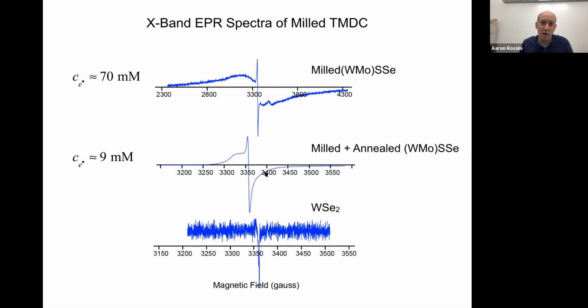We've also done some work on irradiated solids. And we basically see when you get these radicals that have very large g anisotropy, they're just not compatible with CW DNP. I think in the future, with your work with Bob and the things that Xander and Song-Yi are doing, maybe if we can get coherent DNP to work, pulse DNP, then we can start using these really broad radicals to actually polarize nuclei. All right, I will say stay tuned.